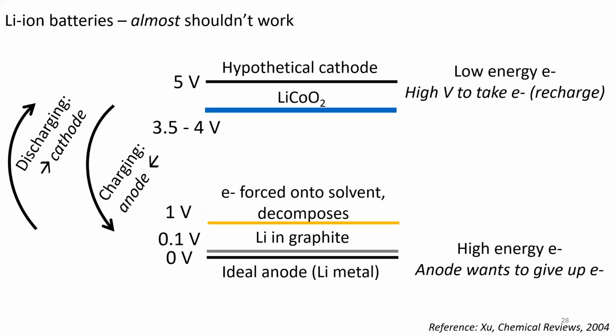It turns out that the electrons in our lithium and graphite anode are so high in energy that they try to put themselves onto our solvent molecules. In chemistry, that's a reduction. These electrons are so energetic that they will force themselves onto our solvent molecules and cause them to break apart. So we shouldn't be able to use these solvent molecules with this high energy anode material.